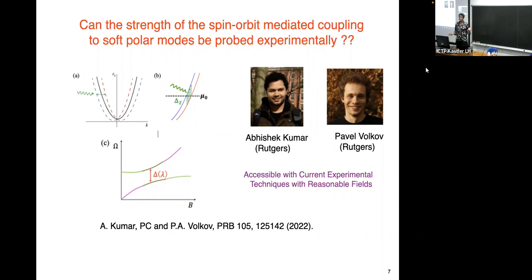Suppose, just very briefly, you did have a Rashba interaction, and let's look in the nearly polar phase. In that case, we would have dynamical spin splitting of the bands. If we turned on a magnetic field, then we would have collective modes associated with the development of spin currents in the polar metal. To make a long story short, we would have collective modes as a function of field, but we would also have our soft mode, and those two would hybridize. The gap will be a function of that spin orbit coupling. We worked out the experimental numbers in terms of fields and all of that, and that can actually be measured.